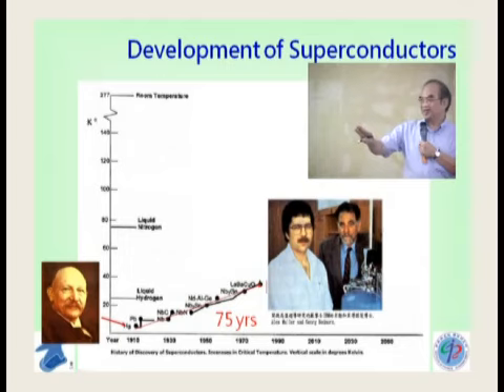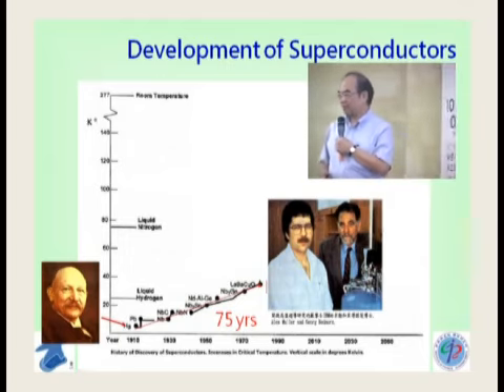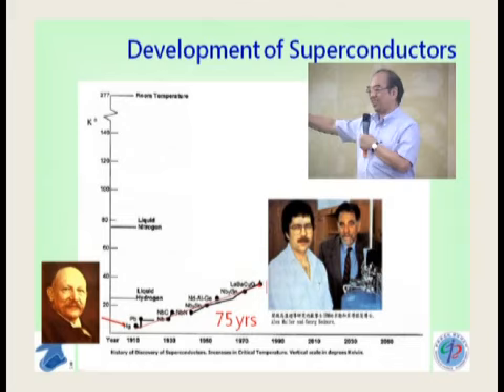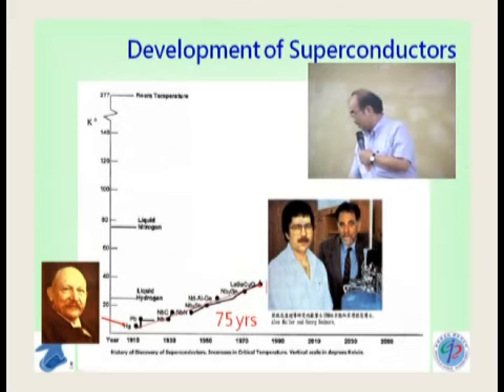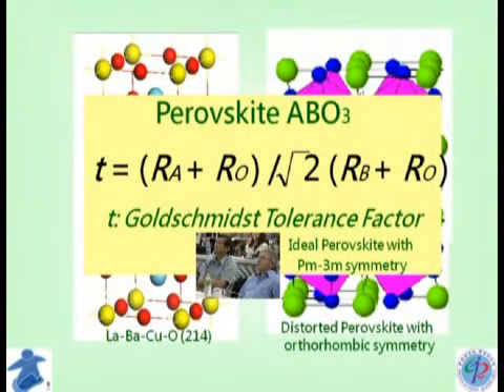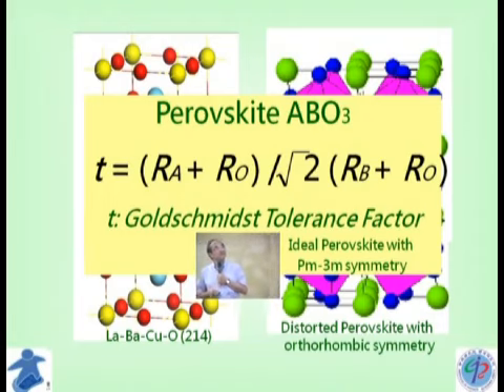And this is what Dr. Bednorz mentioned: the rally really started from 1986 and 1988. By that time, we already knew the structure of this so-called Zurich perovskite. This is a different representation, the octahedron with the copper in the center, but it's still a so-called perovskite structure, although somewhat distorted. This is the ideal case, but if we distort it, it still has this perovskite structure.